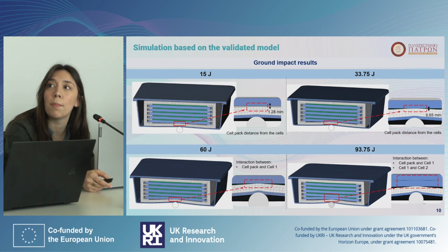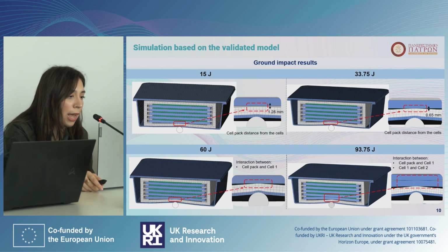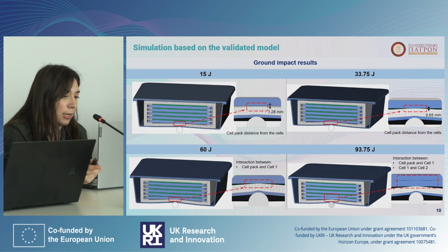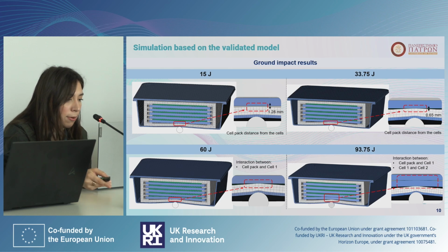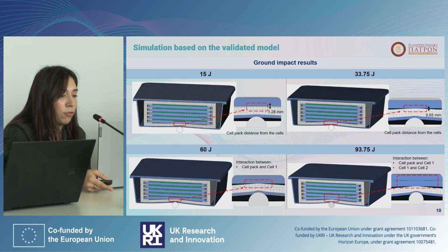So regarding the ground impact simulation results, at the lowest impact energy, the housing shows a maximum displacement of 4.7 millimeters, resulting in a 1.3 millimeter residual gap between the cell pack and the first pouch cell, while as the velocity increases, the gap is reduced to 0.65 millimeters. At a higher impact energy, the housing deformation reaches 7.8 millimeters, and the cell pack now comes in contact with the first cell, which shows localized indentation of 2.7 millimeters.